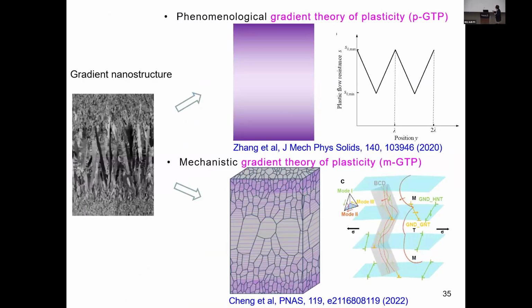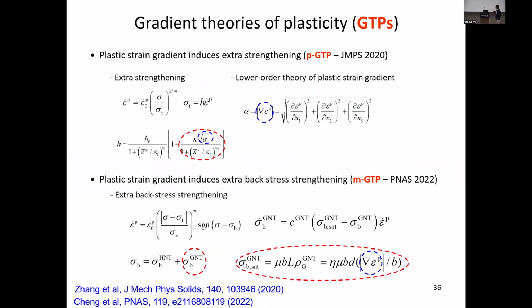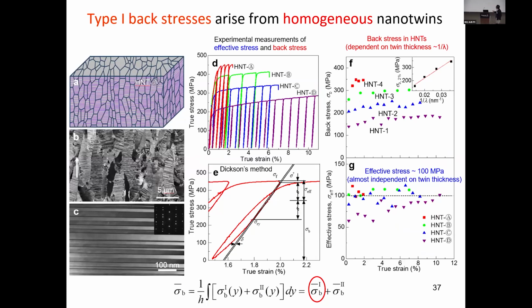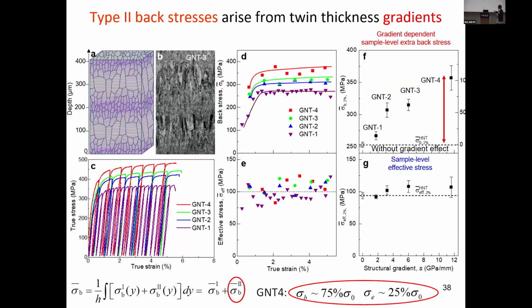So long story short, we developed the so-called gradient model to quantitatively predict this backstress effect. And more importantly, we were able to produce this sample with a precise control of the twin thickness, with a uniform microstructure and with different average twin thickness, that allows us to extract one kind of backstress associated with very fine scale structural heterogeneity. In addition, we were also able to control the structural gradient so that we can further evaluate the additional strengthening effect due to this structural gradient.